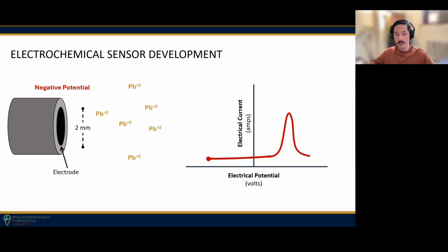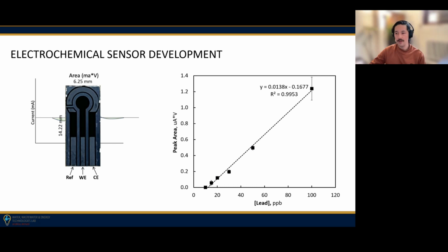So if we are increasing and controlling our potential and measuring the electrical current response, we get this peak here that happens. This process is called anodic stripping voltammetry and differential pulse voltammetry. If Alana, my grad student working on this, is on the call right now, I'm making it seem much more simple than it is, but we'll keep it at a high level right now. So we use anodic stripping voltammetry and differential pulse voltammetry, and we get this peak. And what we can do is measure this peak, both its intensity in current response as well as its area, so the area under the curve.